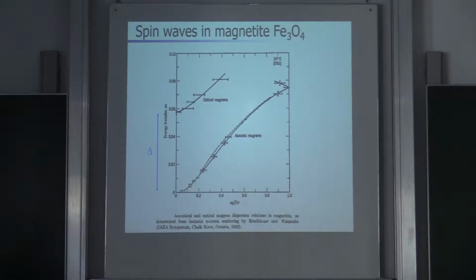Now, if you look at a simple ferrimagnet, like magnetite, for example here, then you see this picture confirmed. Now, the way to measure spin waves is inelastic neutron scattering, because the neutrons see the magnetic field, and they can see the dynamic magnetic field, so they can pick up or excite a magnon, and you can do this as a function of the scattering angles and map the whole spin wave band structure. And here you see some very old results from 1962.